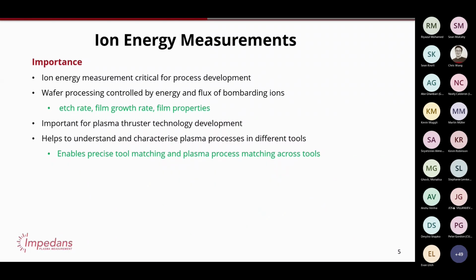Depending on the ion energies and the ion flux, which is the number of ions impacting your wafer per second, you're going to have different etch rates. You're going to have different film growth rates. You're going to have different thin film properties depending on the ion content. It's also important for other things like ion beam tools and plasma thrusters to understand, when I extract ions from this plasma and they then impact my substrate, what do they look like? Are they varying with time? Like if my chamber pressure is up a little bit, is that acceptable or not? This is what you learn with these.